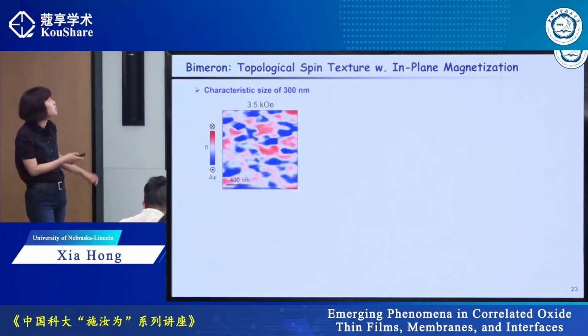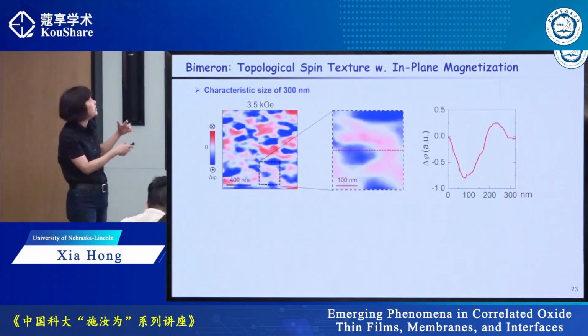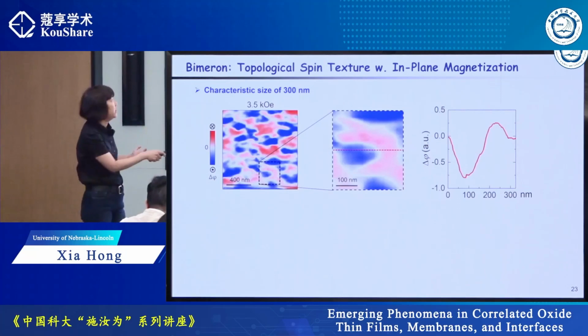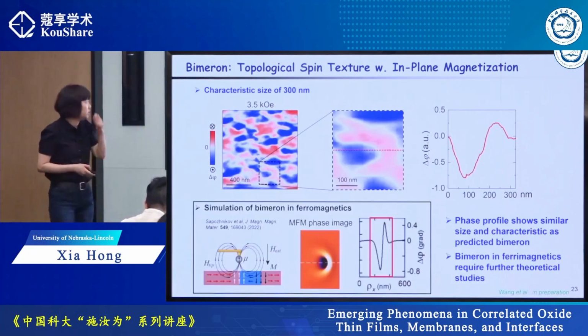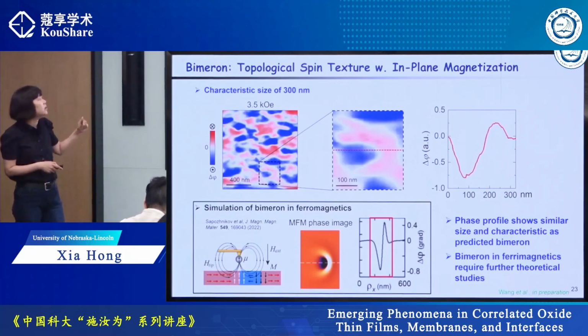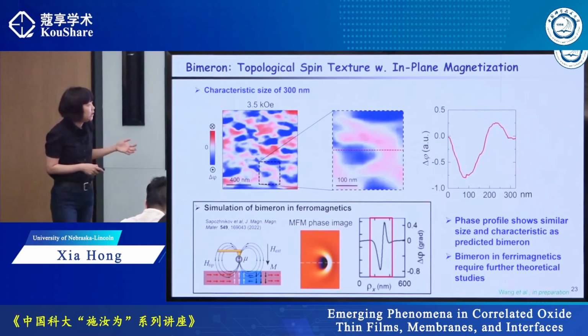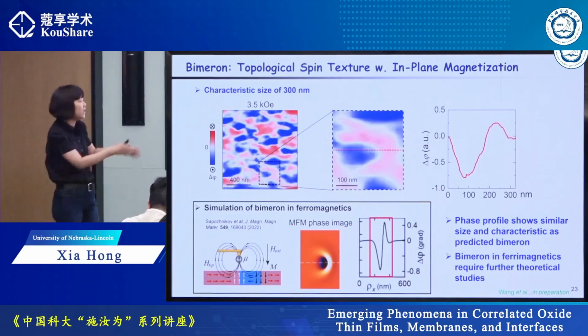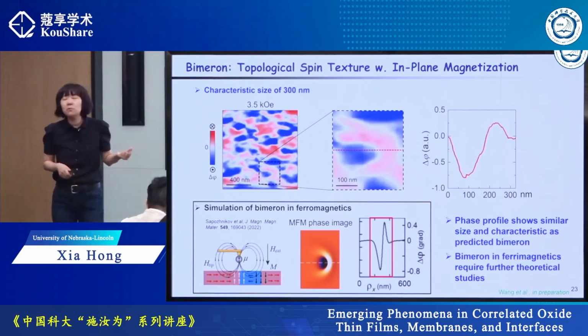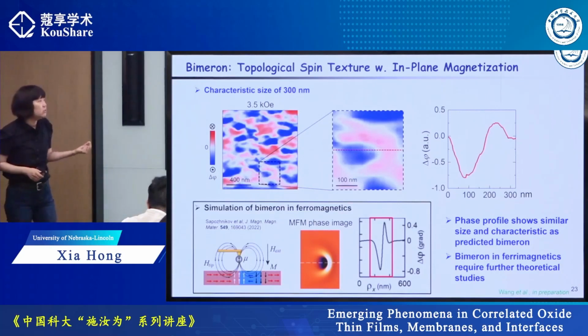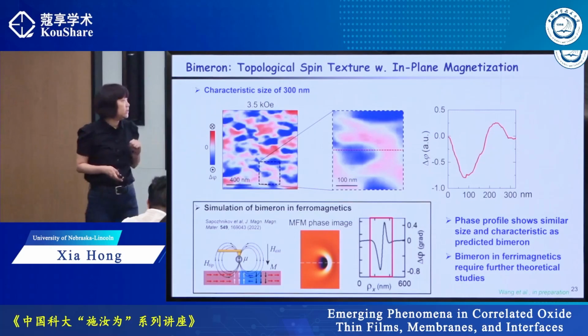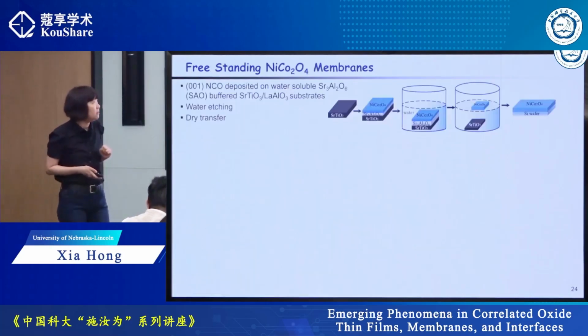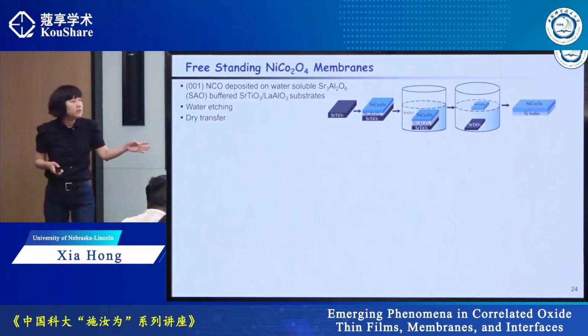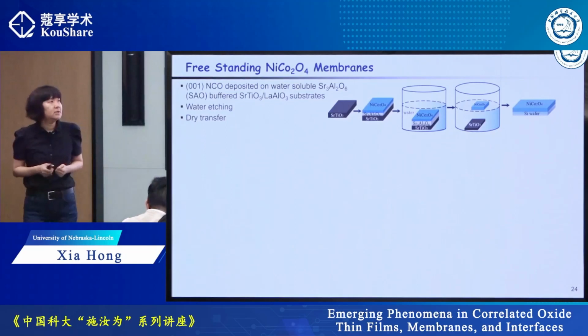Another thing we notice is that it has a characteristic length of 300 nanometer, and it always goes from a valley to a peak structure. So this is a theoretical modeling of bimeron in ferromagnets. And you can see that if we compare the experimental data with simulated data, they have a similar length scale, about 300 nanometer, and this same valley to peak structure. So this gives us confidence that indeed we have observed bimeron structure in this system. So this is how we tune the magnetic anisotropy to host the chiral spin texture.